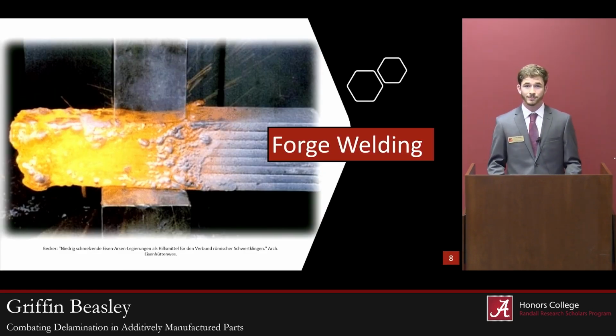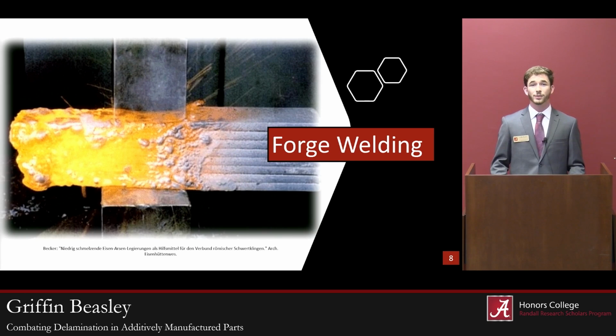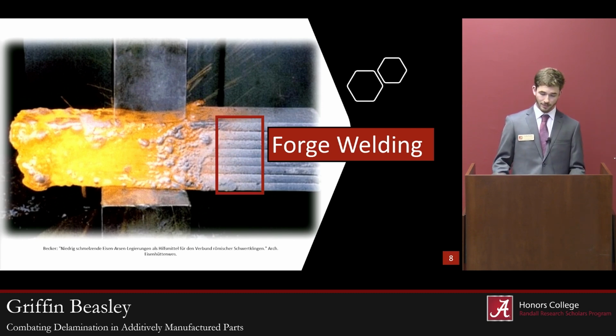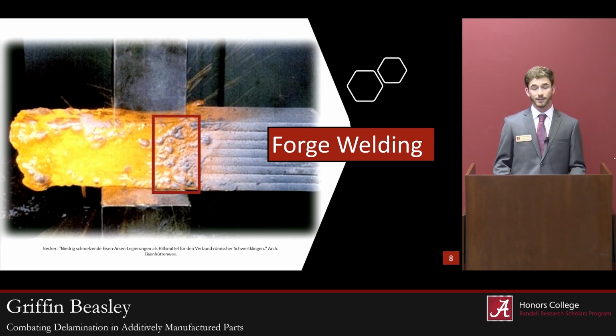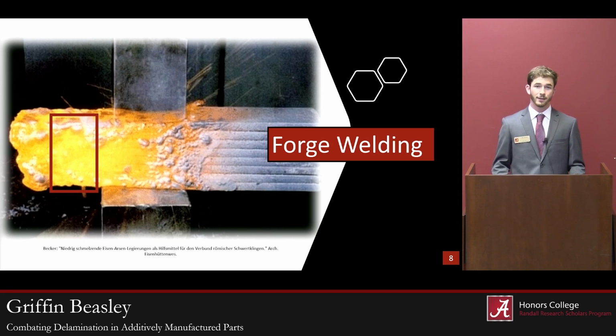What is forge welding? Forge welding is the process of taking two or more pieces of metal, heating them, and striking them together with such a force that a bond is created between the two pieces, making them one solid piece. As pictured in the right side of this slide, these pieces have not undergone the forge welding treatment. And you can see that the layers are very clearly separated and differentiable, and the part is not homogeneous. Versus on the left side of the slide, this section has undergone the forge welding process, the layer lines are not very apparent, and the piece overall is much more homogeneous and solid.